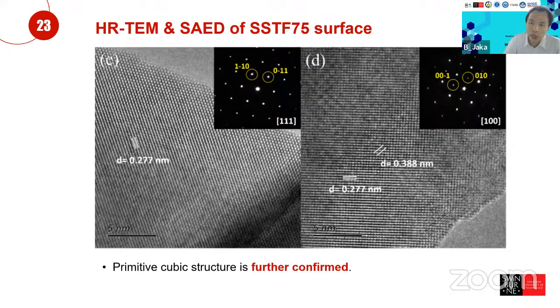With respect to the HRTEM and the selected area electron diffraction in here, we cross-check whether, since XRD shows us that it is a Pm3m structure, the HRTEM and the SAED show that this is a primitive cubic perovskite structure, and they did. Okay, so we basically confirm.